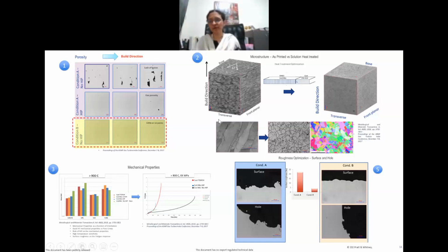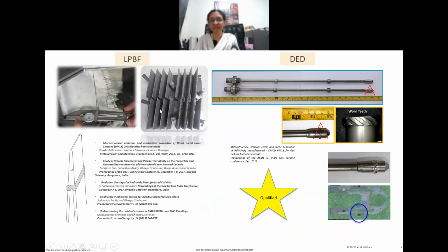The next challenge that I'm talking about here, which we overcame, is to go from an as-printed structure. Of course, most hot section parts, most high-end materials, including steels, nickel-based superalloys, and titanium-based alloys, which are the workhorse alloys for aerospace compressor and so on applications, we need to heat treat. And moreover, when we are joining conventional with additive, as I showed you in this particular case study, actually I forgot to mention, what we decided to do in this application is to cut out this damaged part, both here as well as here, and to use, in this particular case, 3D printed coupons with that required geometry, and then join here with the cast part with manual TIG welding.